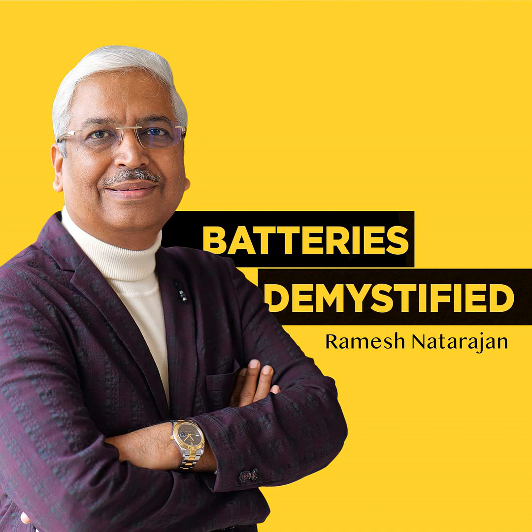So what we're doing right now is we're working with some of the national laboratories around the world to use inelastic neutron scattering to monitor the concentration of our lithium in our electrodes. And then we can test those at different temperatures and under different cycling conditions. It's really cutting edge work that no one has tried before.